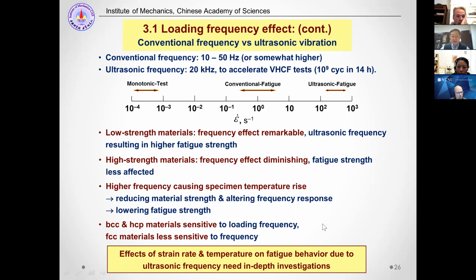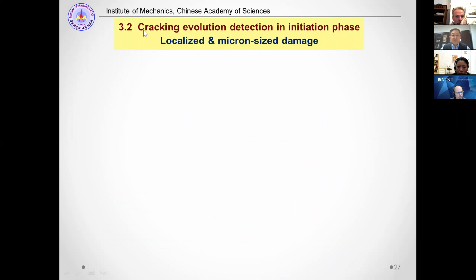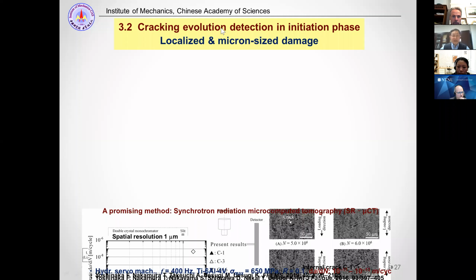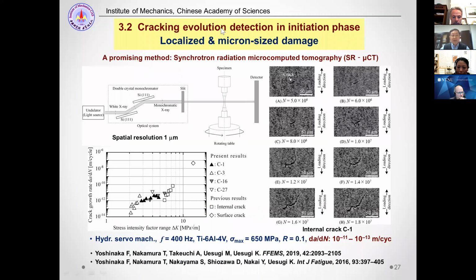It needs in-depth investigations. The second challenge is crack evolution detection in the initiation phase, and a promising method is synchrotron radiation microcomputed tomography. This is from Nakamura's group. They use this new method to observe the defect of crack initiation and early growth, and also they measure the crack growth or extension rates between 10 to the minus 11 and 10 to the minus 13 meters per cycle.